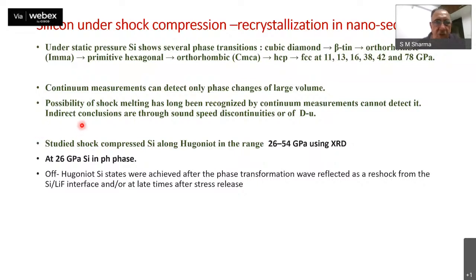change. Possibility of shock melting, though it has been recognized by continuum measurements, could not be detected definitely by the continuum measurements. Only indirect conclusions could be deduced through the sound speed discontinuities, basically because once material melts, it does not have shear strength, so the bulk sound speed really falls down. So on those kind of deductions, one could kind of state that silicon melts under shock compression. However, there's no explicit confirmation of that.